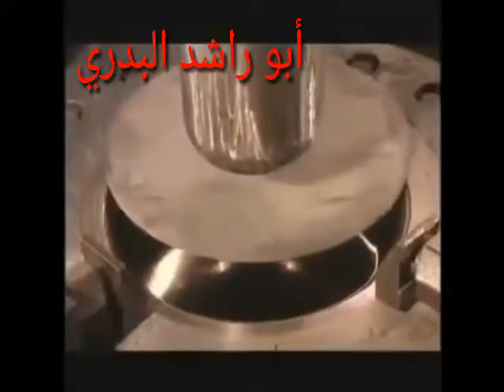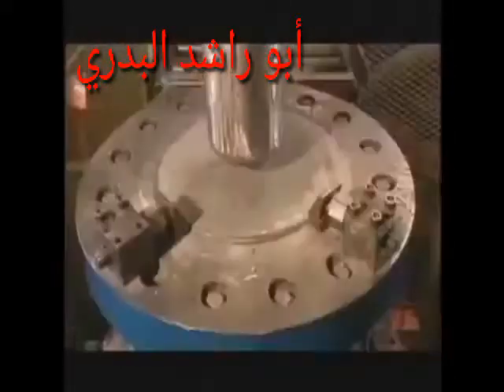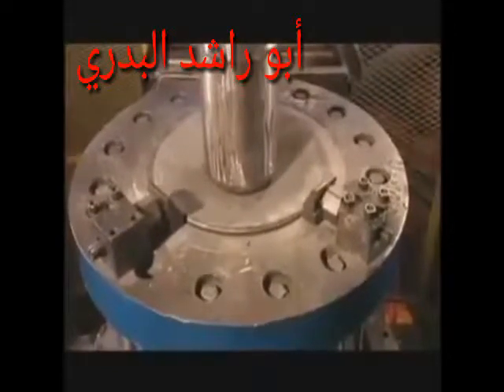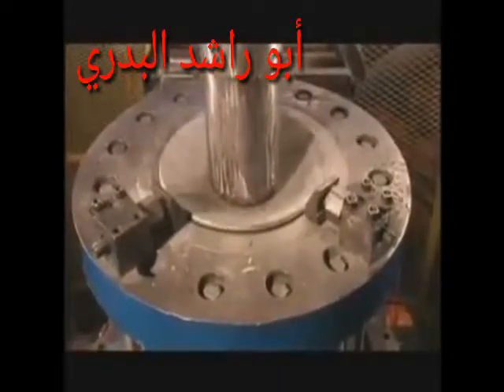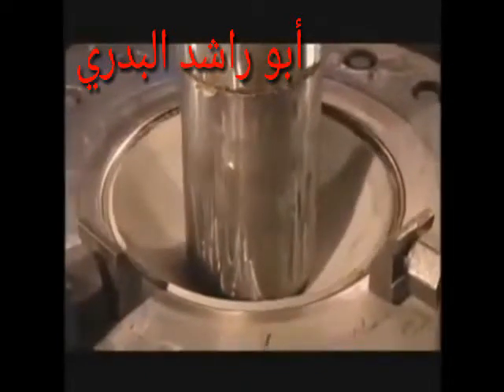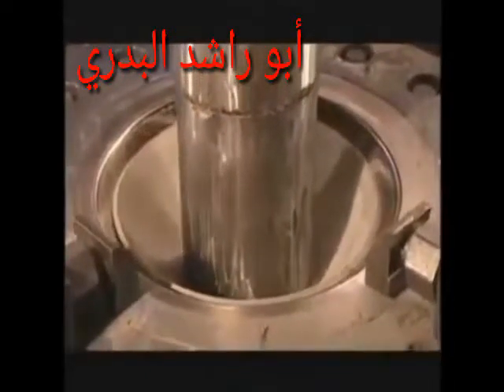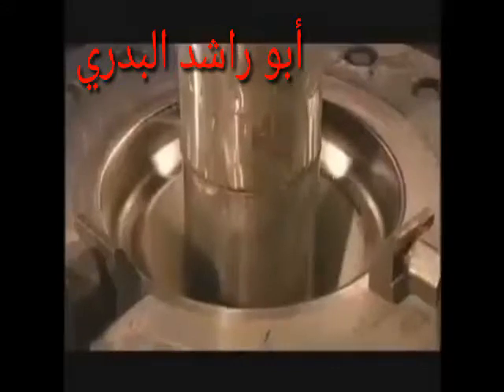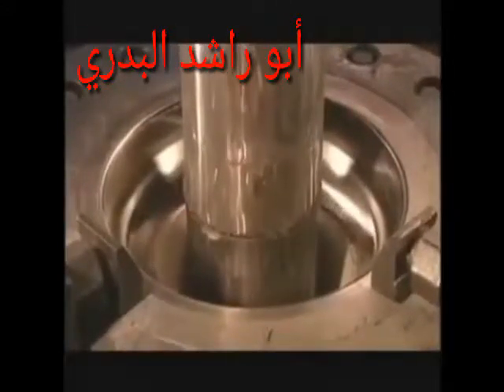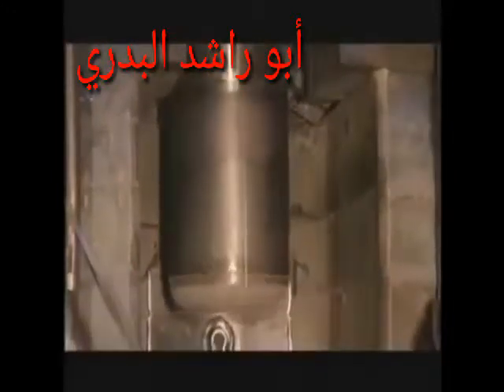They are centered over an intake die for the first of 2 or 3 deep draw and ironing operations. This tooling is made from either high-grade tool steel or it is sometimes inserted with carbide to provide better wear resistance. The first draw or cupping press utilizes up to 800 tons of force to complete the draw. After the cup exits the last ironing die, stripper jaws are engaged to remove the cup from the mandrel.